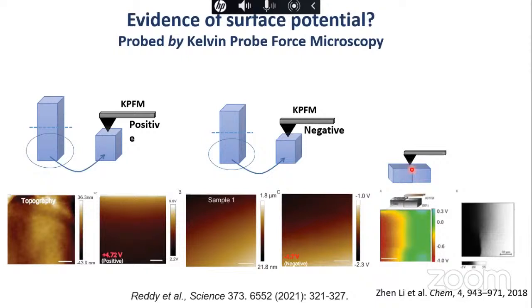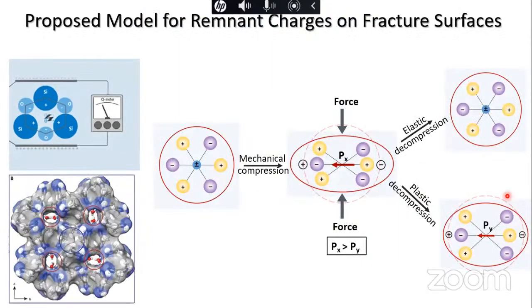Then we took a crystal, broke it, and put the pieces together, and we measured the crack junction. We found that on one side you have one charge, and on the other side you have the opposite charge. This also tells us that at the crack junction you have complementary charges. So we proposed this after we looked at the crystal structure and studied it in detail. We found that this is a piezoelectric crystal, which means it is a non-centrosymmetric space group.